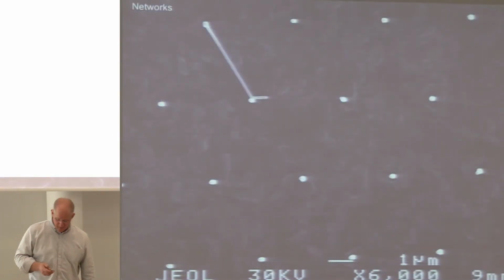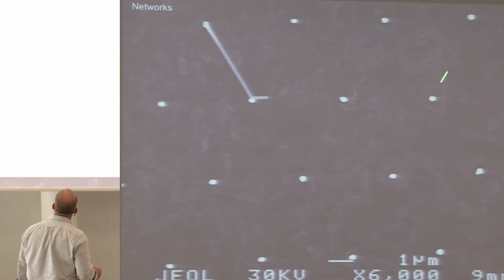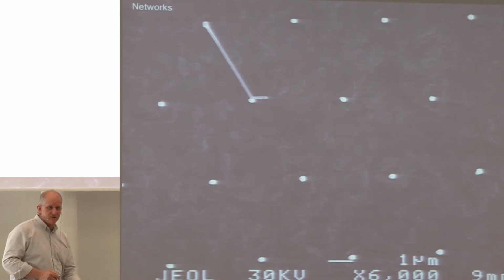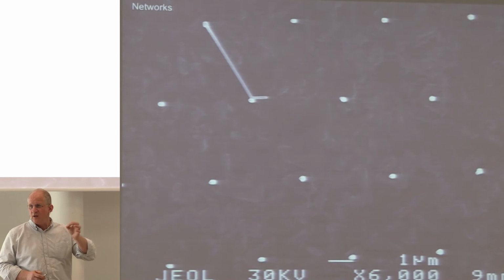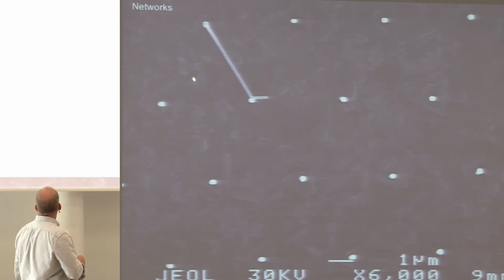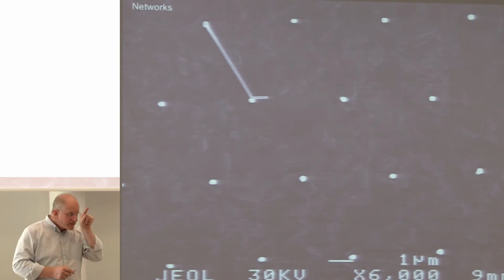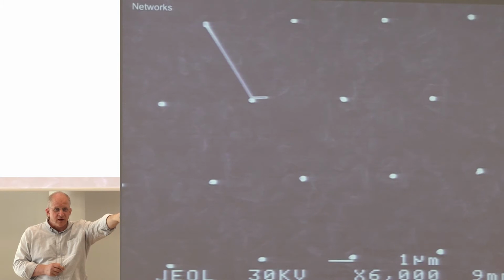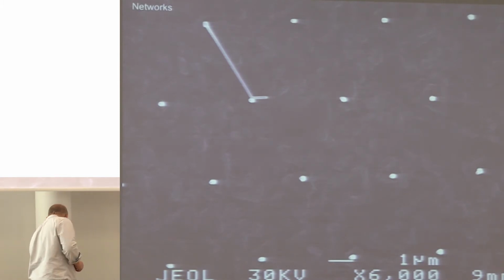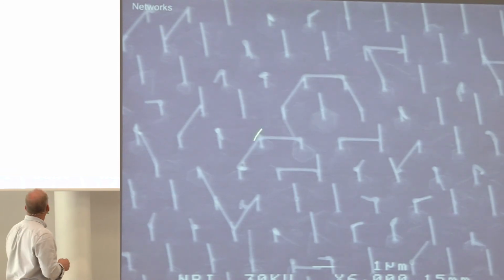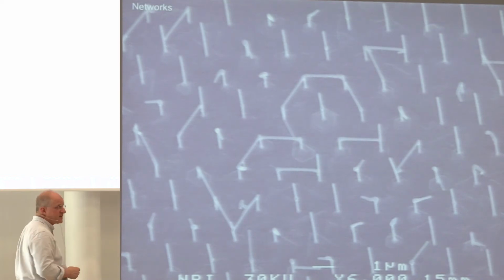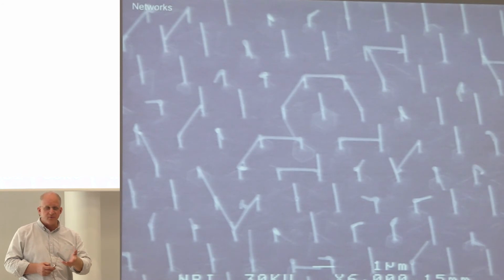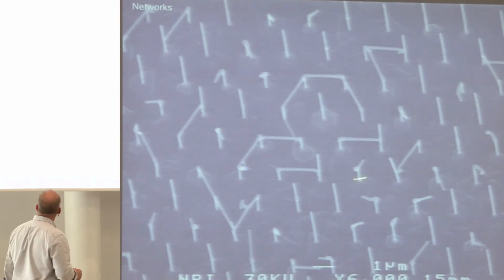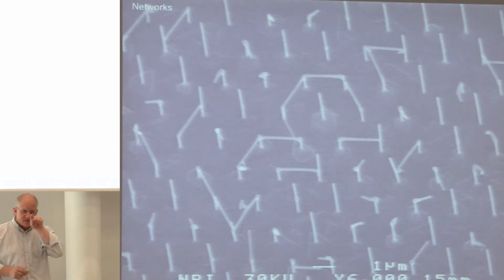To make matters even more remarkable, if you put the catalyst gold particles in a hexagonal orientation on the substrate, that is, you just deposit, using electron beam lithography, the spots where you want the wires to grow in a hexagonal pattern that's registered with the hexagonal orientation of the crystal itself. Then, when the wires start growing out of the side of one of those facets, they'll aim themselves directly at one of the other wires that's growing up from the side. And in doing so, they'll begin to produce a network of wires that grow in this kind of orientation, so that you could even have complicated and, in particular, T-shaped structures, which are the key to these braiding operations and looped structures, etc. So this is far from a perfect crystal, but it's enough to do demonstrations of braiding because we have this epitaxial growth from this aiming of the lateral wire.